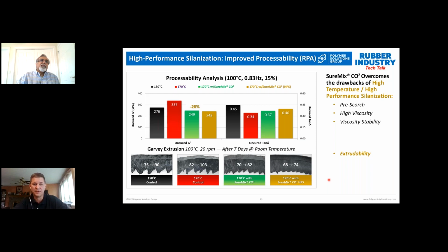Okay, if we look at the processability of these compounds, again, we're looking at RPA, uncured processing. You see the increase in the viscosity going from 150 to 170 degrees C, from the black bar to the red bar, and you see the decrease in the viscosity using SureMix CO squared in the green bar at 170 degrees C, and then with the reduction in the silane, you also see that nice low viscosity. So in both cases, using SureMix CO squared, whether it's at the control level of silane or at the reduced level, you see a viscosity that's lower than the control compound, even though we're processing and performing silanization at 20 degrees higher temperature.